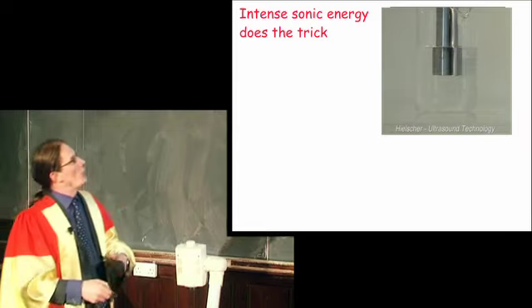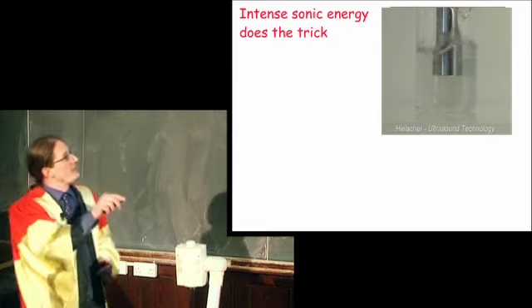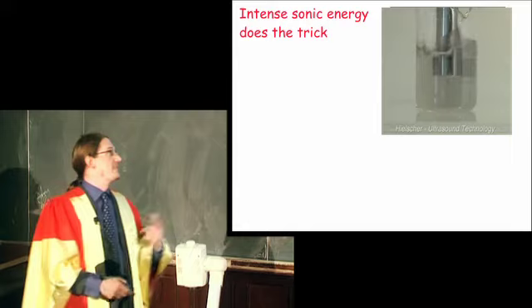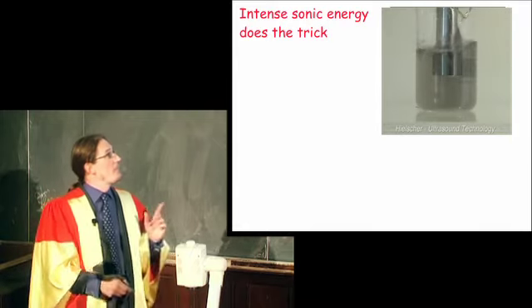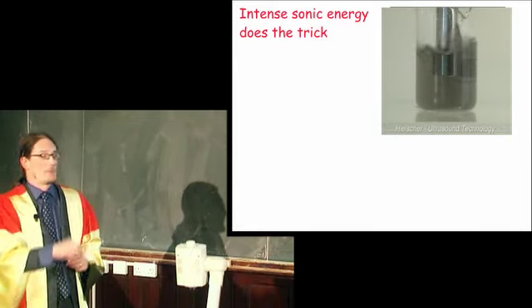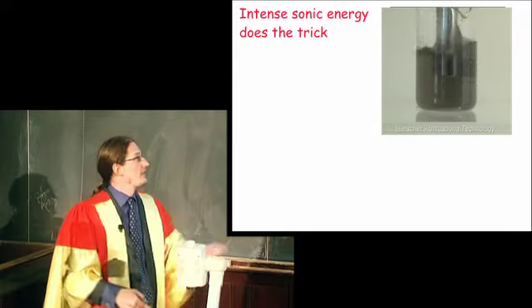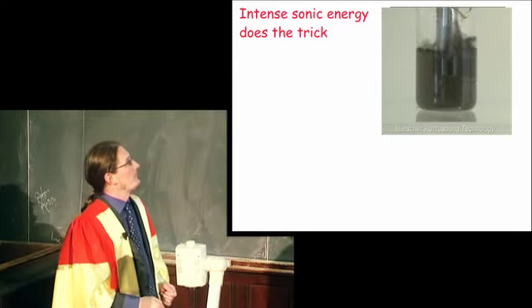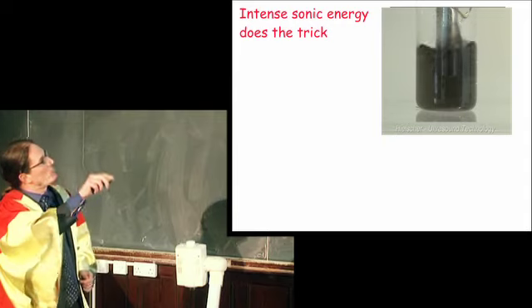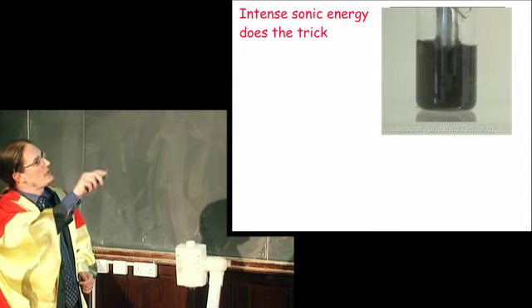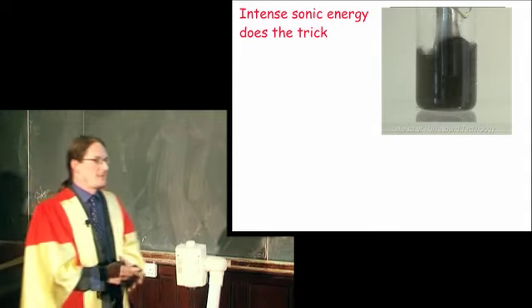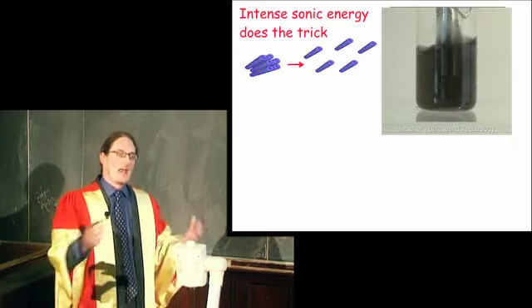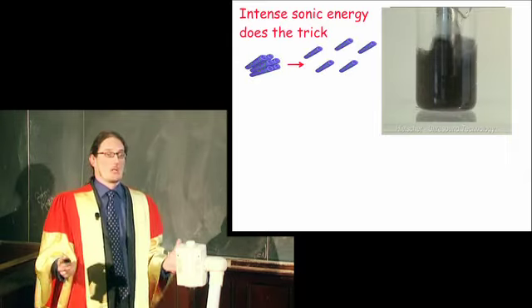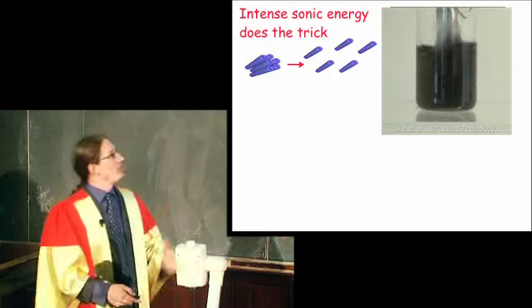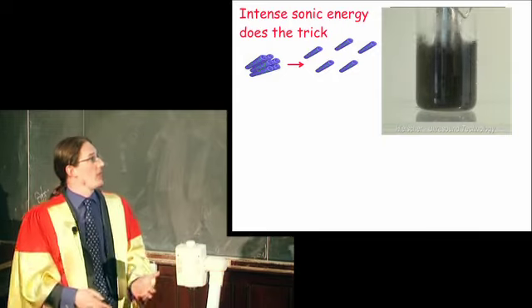This is a bit like the probes that doctors use, except the power output of this probe is, well, A, it's at a different frequency, and B, this is 10,000 times as powerful as the sort of thing that you use to image babies. But you can see that when I put this probe in and turn it on, the liquid goes black. And the reason it goes black is that the nanotubes have been broken out of their bundles and individualized. And all these individual nanotubes are now absorbing light, and the thing turns black.